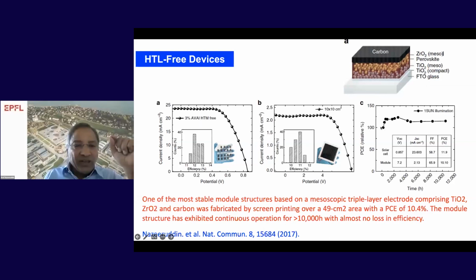But if you take the large area of size 10 by 10, the efficiency is close to 10%. However, if you look at the stability, this is the highest stable performing perovskite composition in triple layer configuration, which gives 12,000 hours stability under outdoor conditions. So this is an extremely stable performing perovskite configuration. However, the efficiencies are lower.